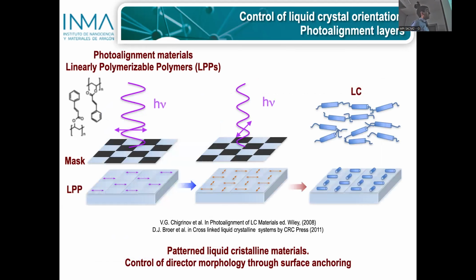Another method to get alignment in liquid crystals is with photoalignment layers, like these polyvinyl cinnamate materials. They are called linearly photopolymerizable polymers, because if we expose them to UV light, and later we put a liquid crystal on top, the liquid crystal will follow in some way the polarization of the light. Depending on the material and the dose, the liquid crystal molecules can be parallel to the polarization or perpendicular, but in any case, the material is able to register this polarization of the light and transfer it to the liquid crystal. So advantageously, you can use photolithographic techniques to generate complex patterns in the polymeric layer that later will be transferred to the liquid crystal that we put on top.